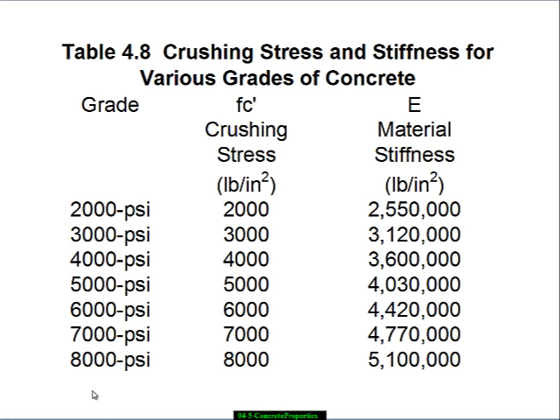In the city of Raleigh, you typically will have 3 KSI for footings that are perhaps oversized because of bad soil conditions. 4,000 PSI is generally the common grade. Every once in a while you can get 5,000 PSI, but usually somebody's eyebrows go up when you say that. On the other hand, it's not uncommon in Chicago — where they have really great aggregates and a wonderful infrastructure for delivering concrete — to be able to buy 10,000 or 12,000 PSI concrete. So these numbers are extremely variable.